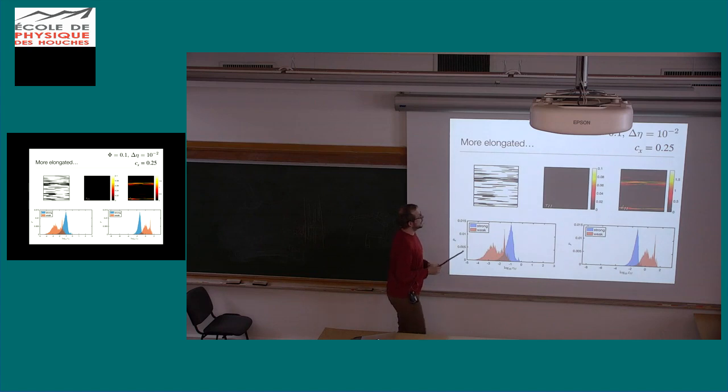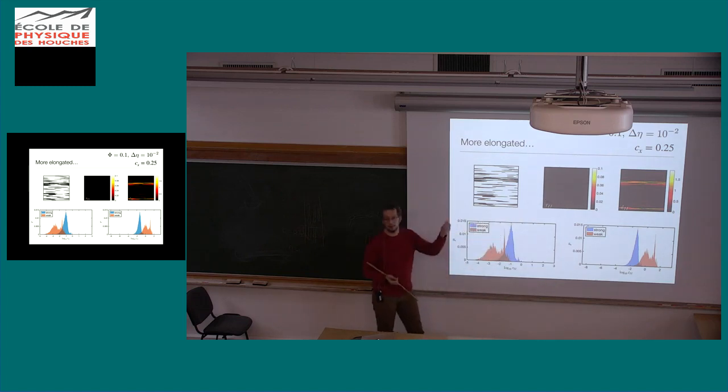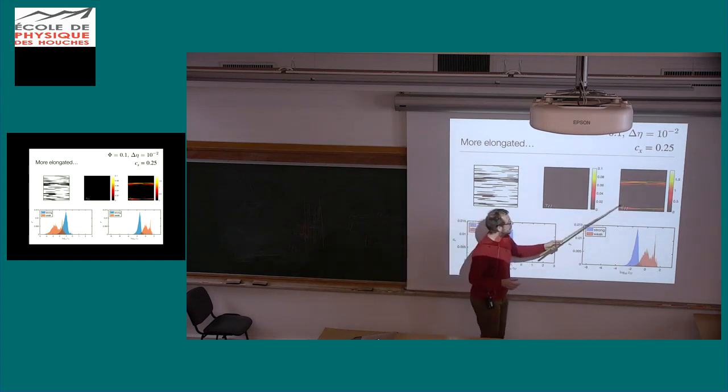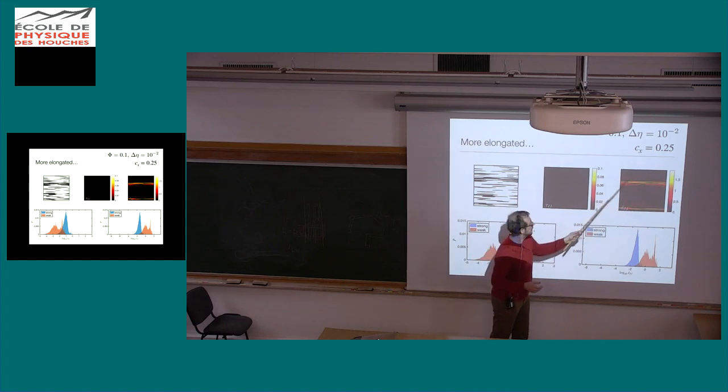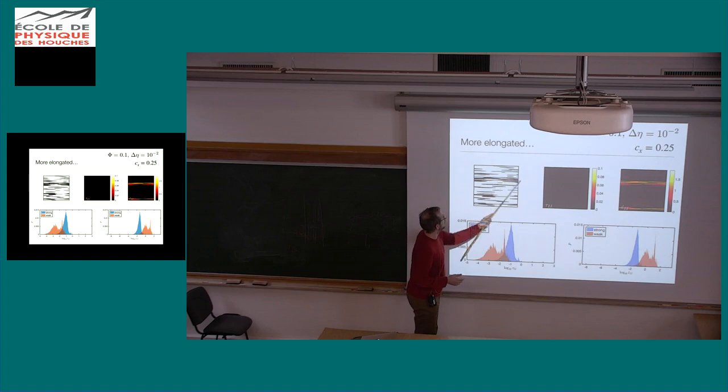And you see already that this is completely black, except some speckles here and here. So that means that actually your stresses drop significantly compared to what you saw before. And when you look at the strain field, you see that all the deformation is basically in those bands here, which correspond to the connecting clusters here and here.